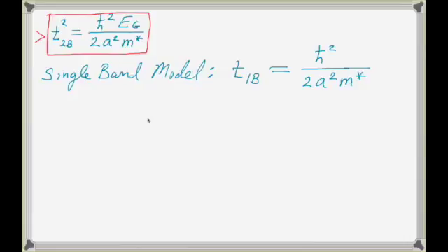And in fact, the off-diagonal matrix element in the two-band model is just the geometric mean of the one you had in the one-band model times the band gap. I've never seen anyone write it down like that, and I'm not sure if it has too much physical significance, but all I see immediately when I write it like that is that that matrix element is increasing as the square root of the band gap. I'm not sure how to interpret that.